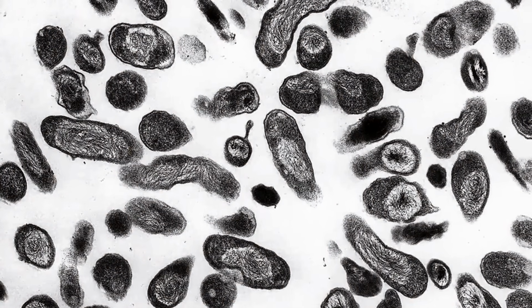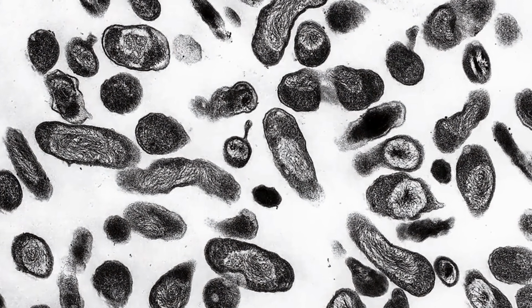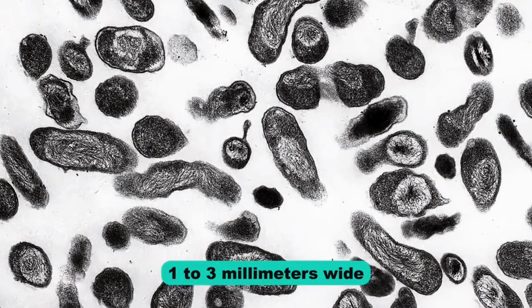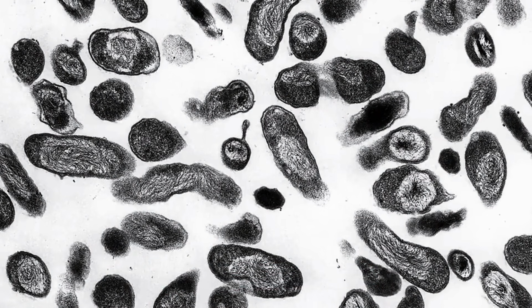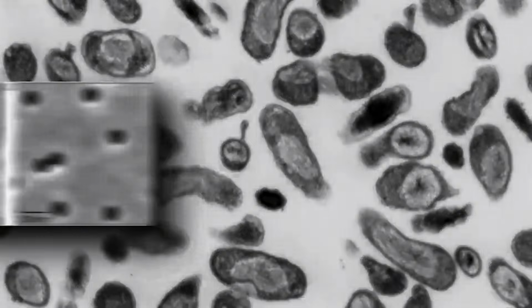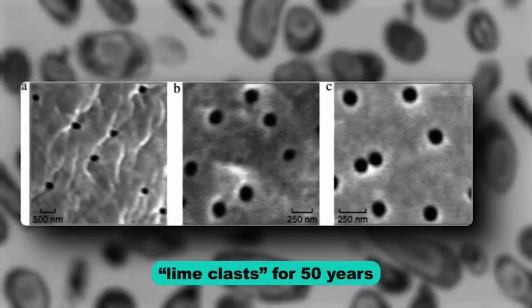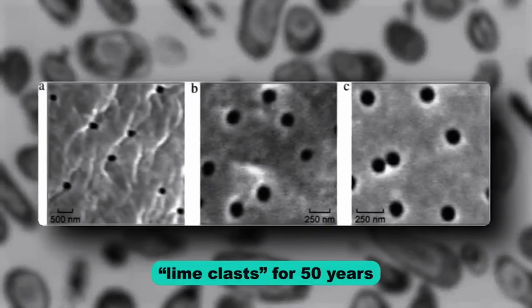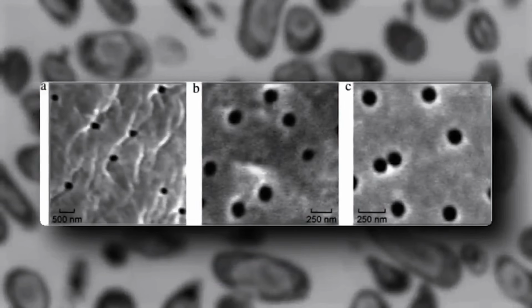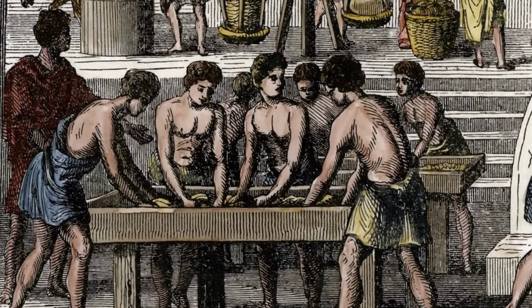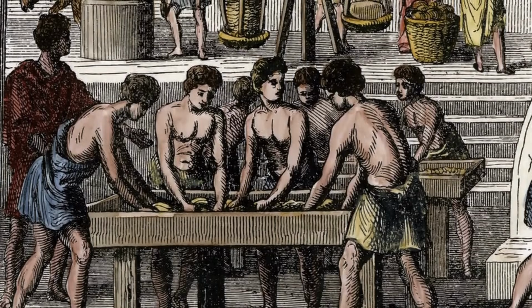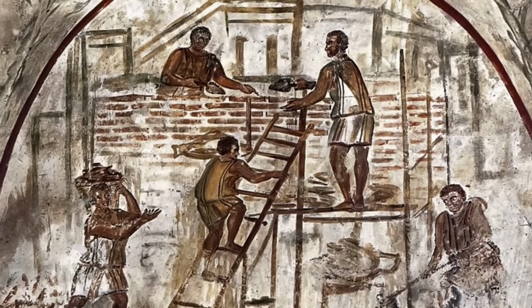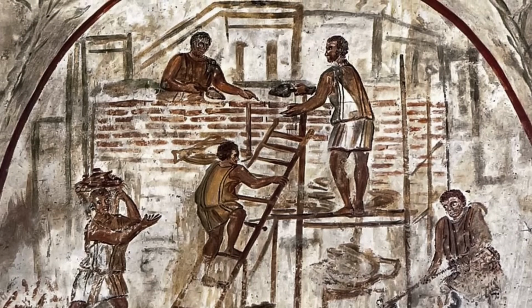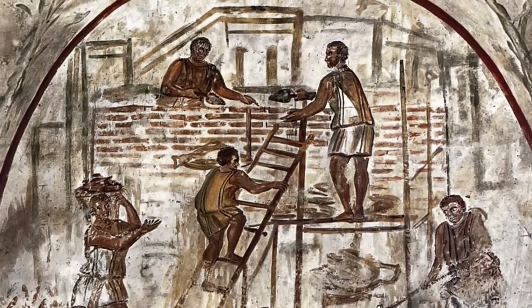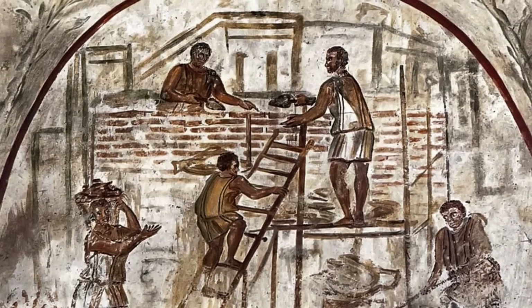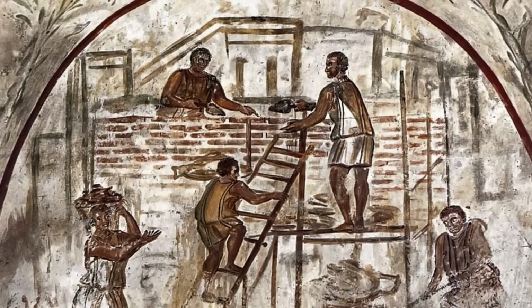Under the electron microscope, the samples kept showing small white chunks, 1 to 3 millimetres wide, embedded in the concrete matrix. Modern chemists had been calling these lime clasts for 50 years and assumed they were defects. Sloppy mixing by Roman workers. A flaw in the recipe. Masic ran X-ray diffraction. He tested fresh concrete mixed 3 different ways. The lime clasts were not flaws, they were the entire point.